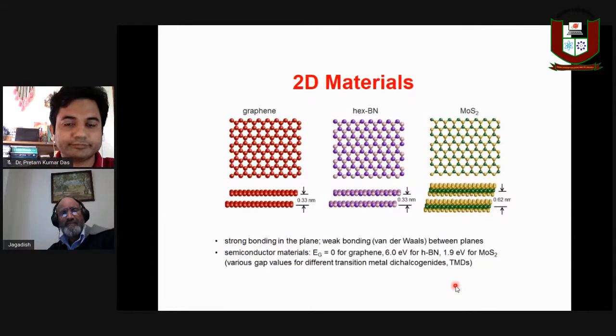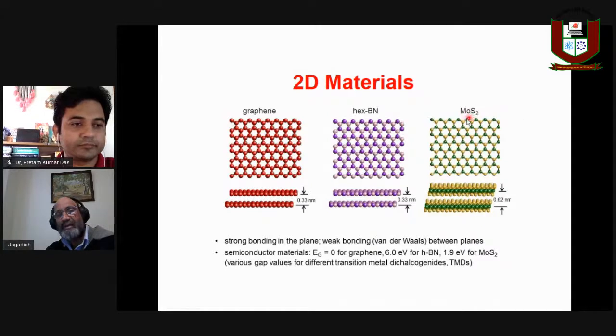With the development of graphene, many people have been looking at what other materials are available. Graphene acts more like a metal because it has a zero band gap, and by introducing strain, people have shown that they can increase that band gap. Another material, hexagonal boron nitride, with boron and nitrogen organized in a hexagonal format, acts like an insulator. Whereas molybdenum disulfide acts like a semiconductor. So by choosing different kinds of these 2D materials, you can change the properties to be like a metal, an insulator, or a semiconductor.